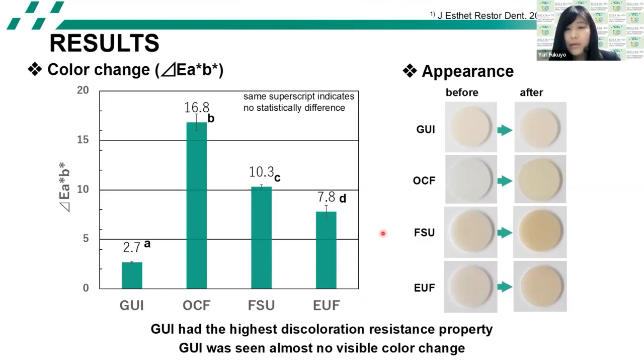And focusing on the visual inspection I show in here, GUI showed apparently less discoloration compared to the others, and in GUI almost no visible color change was seen. This result reflected a previous study, which summarized that the color appearances are almost the same if delta E is 2.7 or less.